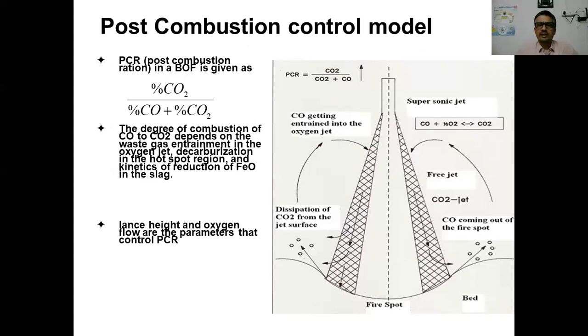After the impact of the jet, the carbon monoxide gas is coming from the impingement zone. But this carbon monoxide gas may get entrained into the oxygen jet while moving upward, and that entrainment will depend on the condition above the metal surface. What could be the conditions? The first condition is that if the liquid metal is covered with enough volume of slag, then the possibility that this rising carbon monoxide gas bubble may get entrained with the jet is more.